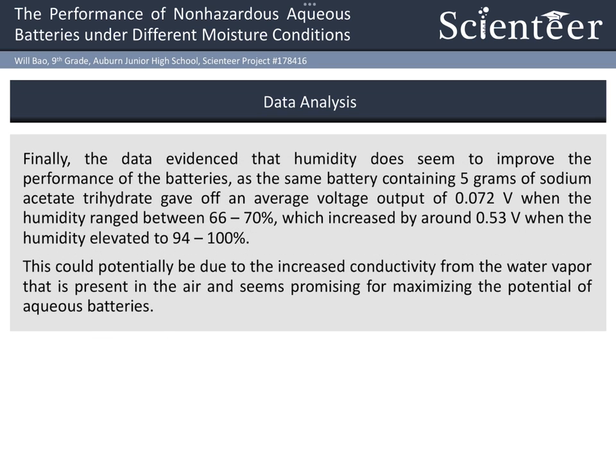Finally, the data showed that humidity does seem to improve the performance of the batteries, as they had a significant increase in voltage output after the humidity range was raised from 66 to 70% to 94 to 100%. This could potentially be due to the increased conductivity from the water vapor that is present in the air, and seems promising for maximizing the potential of aqueous batteries.